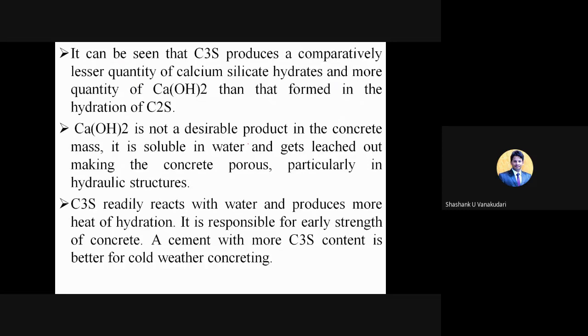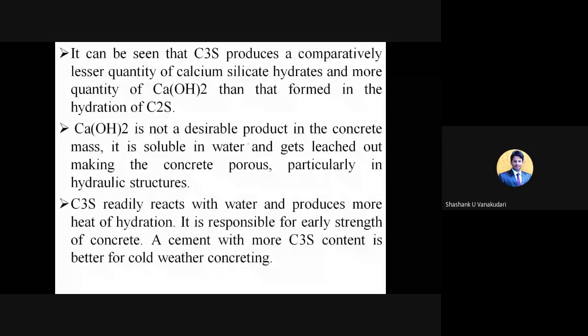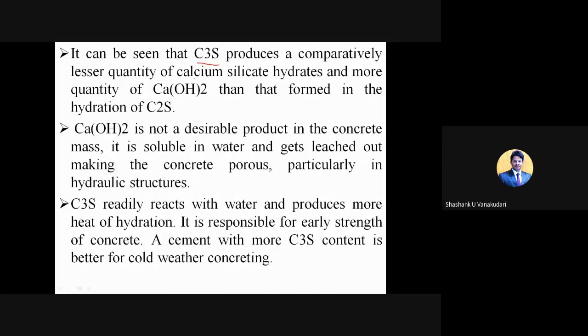Okay, and it can be seen that C3S produces a comparatively lesser quantity of calcium silicate hydrates and more quantity of calcium hydroxide. So when C3S reacts with the water, it forms a lesser quantity of calcium silicate hydrate, but the byproduct it forms is calcium hydroxide, Ca(OH)2. This Ca(OH)2 is mostly generated by the C3S compound. Okay, and this calcium hydroxide is not a desirable product in the concrete mass. It is soluble in water and gets leached out, making the concrete porous, particularly in hydraulic structures.